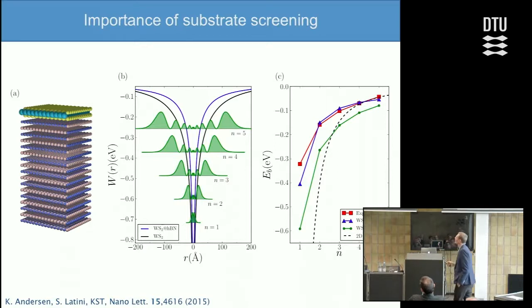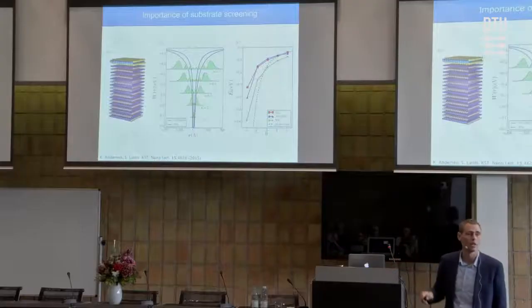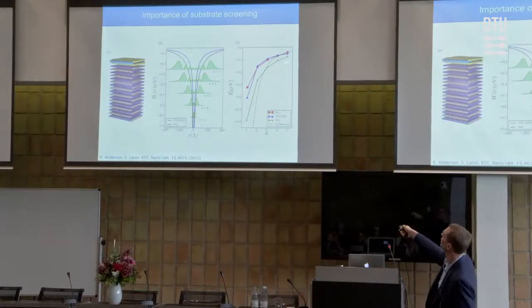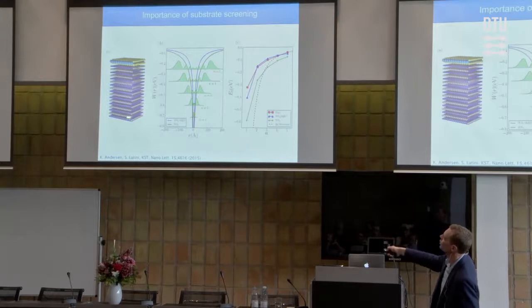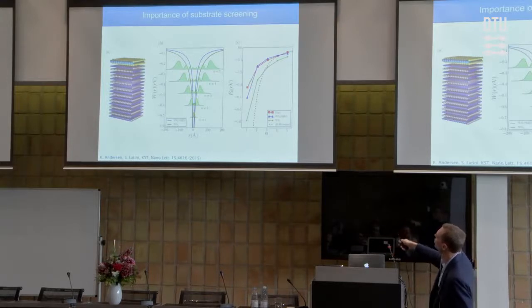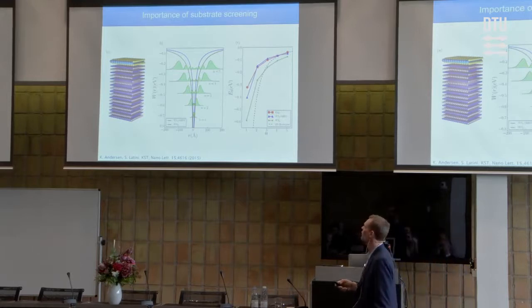I should add here that it's very essential to take substrate screening into account. If we do these calculations for an isolated layer of tungsten disulfide, we get the green energies over here. The experiments are the red. If we use the QEH model to include the screening from the substrate, what we get is the blue here, again in very good agreement with the experiments.